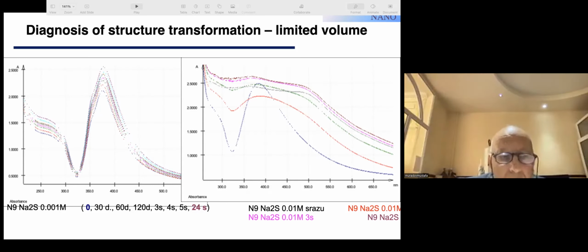layers. And in case of low concentration of sodium sulfide, you can form thin layers, and you don't destroy the silver nanowire structure. When you increase the concentration of sodium sulfide solution, the spectrum changes more, and this spectrum looks like the silver sulfide spectrum.